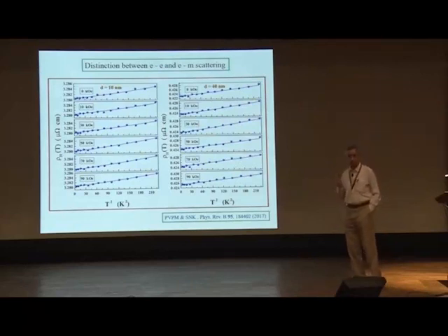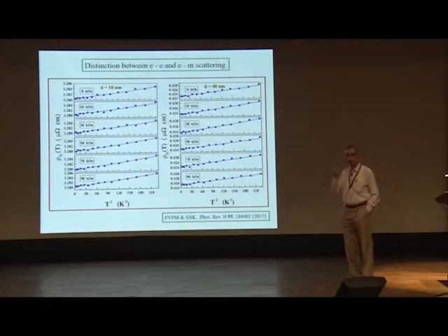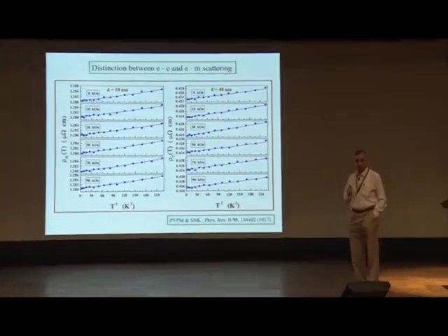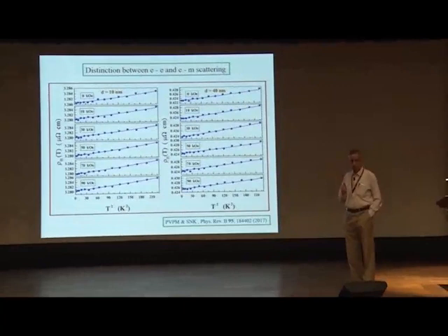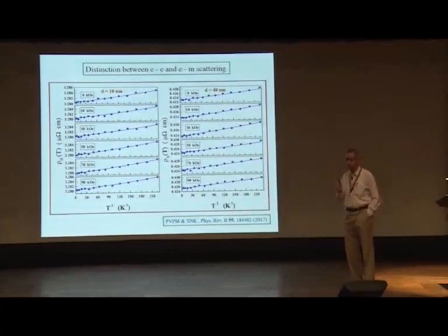But what we see is actually, if you go technically, then electron-electron scattering accounts completely for the residual and the intrinsic resistivity up to about 10 Kelvin. Above that, phonon scattering also starts picking up. Okay, that has to be taken into account to get the full picture.